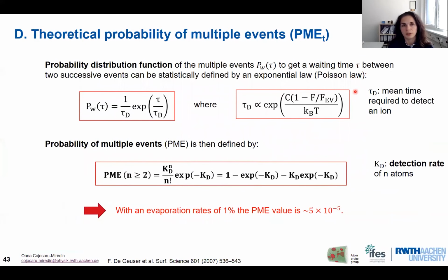Now let's speak about the theoretical probability of multiple events. The probability distribution function is given by an exponential law, a Poisson law, which depends on the mean time required to detect an ion, tau d. Now, if we work further on this exponential law, we can develop the probability of multiple events, and we can define it depending only on the detection rate of the n atoms.